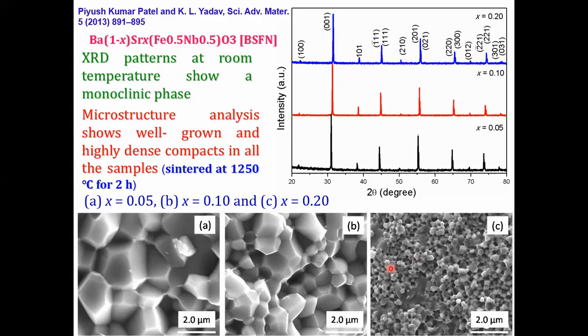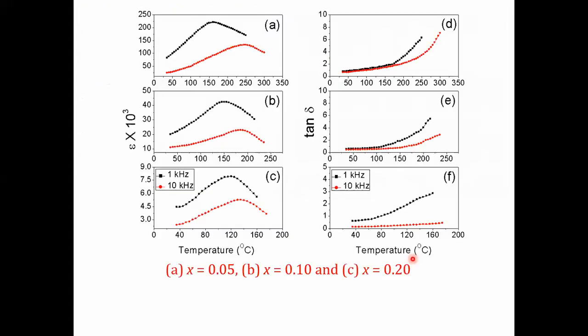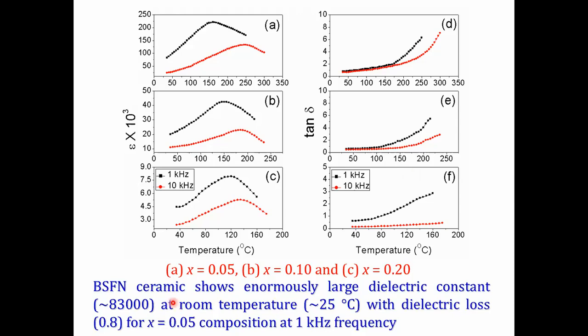When there are a large number of grain boundaries, dielectric constant will automatically be decreased. This we can see in the dielectric measurement. If you see the dielectric constant of 0.05 doped strontium, then 0.1, then 0.2, and these are the losses. In the 0.05 sample, around 83,000 dielectric constant at room temperature with dielectric loss of 0.8 at 1 kilohertz frequency. In the BFN, it was 33,000, but small amount of strontium doping has increased its value to 83,000, at 1 kilohertz. That is the effect of doping.